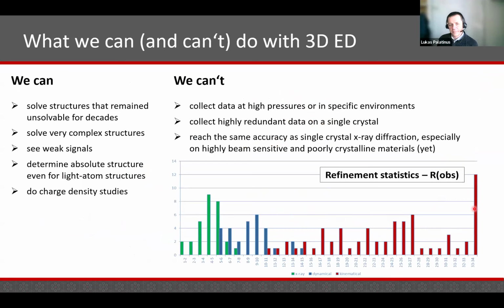So here is a little summary of what we can and what we cannot do with 3D electron diffraction. So we can do a lot. We can solve structures that remained unsolved for a long time, including very complex structures. We can see weak signals like hydrogen atoms. We can determine absolute structure, even for light atom structures. And we can even, as you will see, do charge density studies using electron diffraction data.